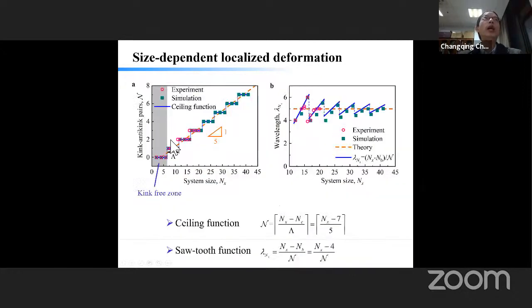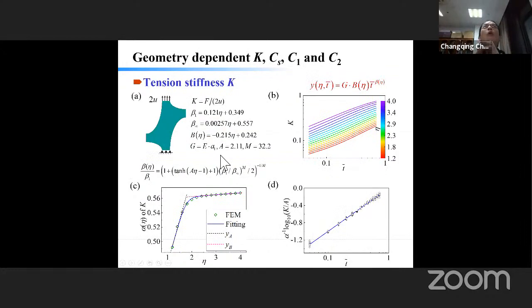So we summarize the size effect on the localized deformation. You can see when the specimen size is less than 5, down here, you will get a kink-free zone. So if you want to observe highly localized deformation, you have to use a very big specimen, at least big enough. Now we come to several geometrical parameters, K, CS, C1, and C2. I haven't talked about the details. I'm going to go down a little to how to get the parameters in the previous theoretical model.